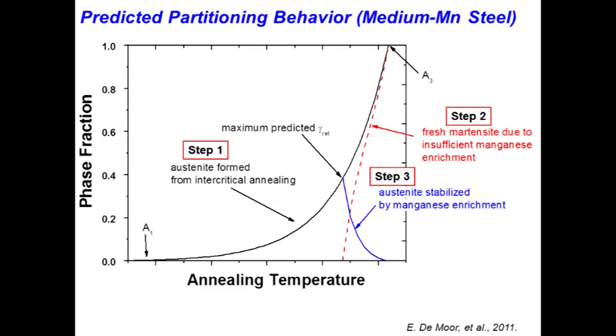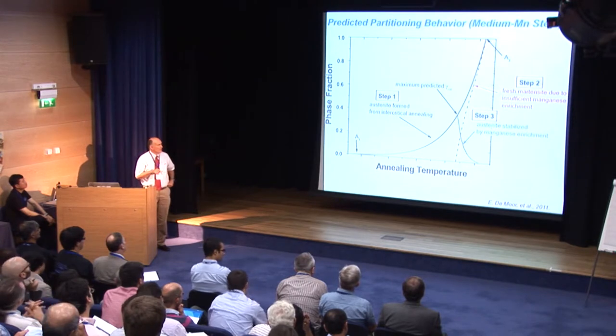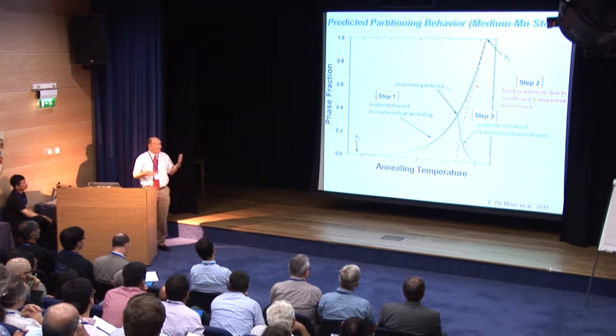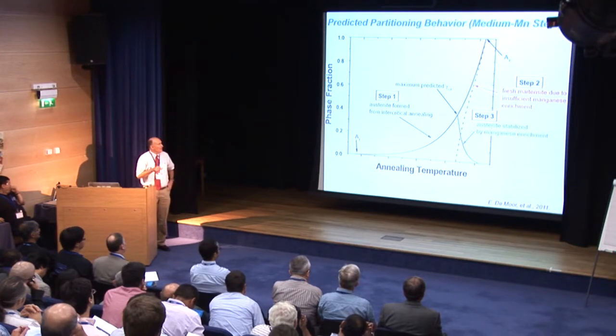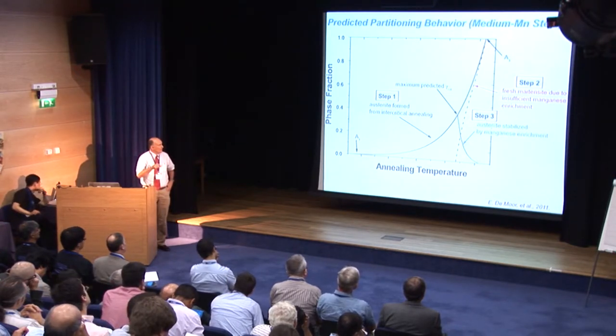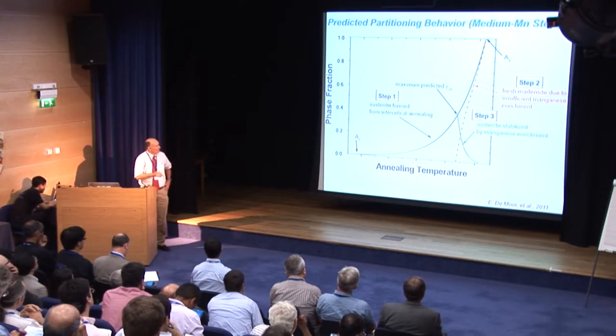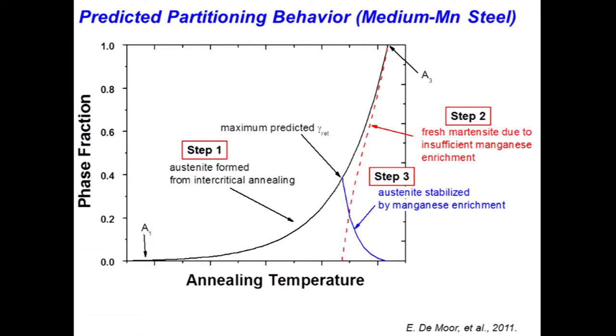It's basically the same kind of behavior, except in this case, the ferrite-austenite fraction is controlled by the annealing temperature. So the greater the annealing temperature, the more austenite we have. And then if manganese can partition into that austenite, the austenite is enriched with manganese, but it really depends on the phase fraction. So the more austenite that you have, the less manganese enrichment that you have. And so the less stable is that austenite in terms of remaining at room temperature. And so depending on its stability, it could transform to martensite during the final quenching. If we again subtract this from the austenite curve, we end up with this black and blue function that tells us how much austenite would remain at room temperature. So a very similar application of the same fundamentals to a completely different class of steels.